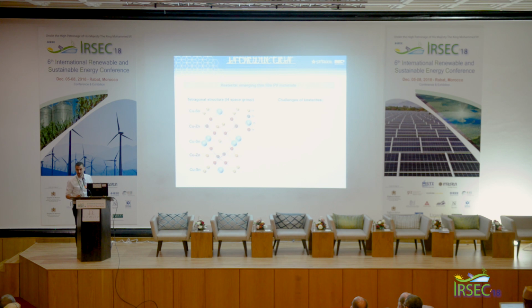But this is most probably the most complex family of materials studied so far, fully inorganic, for thin film photovoltaic application. So of course we have a lot of challenges to solve. Among them, and Susan already summarized extremely well almost all of them, is that copper and zinc are isoelectronic elements, so they easily exchange in the lattice, forming this kind of defects and disorder like copper on zinc and so on.